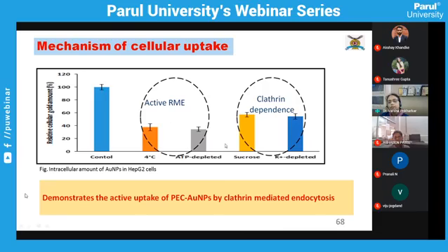Also, when we added sucrose and potassium depletion to the medium, it established that it is clathrin dependent, because clathrin mediated processes require sucrose and potassium. So this clearly demonstrates the active uptake of the pectin reduced gold nanoparticles by clathrin mediated endocytosis.